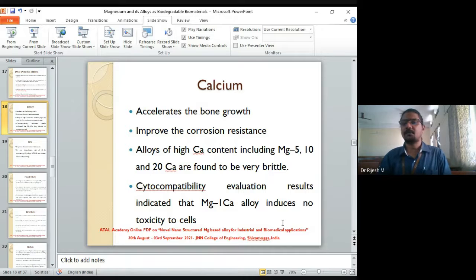Alloys of high calcium content, including magnesium with 5, 10, and 20 percent calcium, are found to be very brittle. Whenever you add calcium, corrosion resistance increases, but mechanical properties come down, is what we observe. Cytocompatibility evaluation results indicate that the magnesium 1 calcium alloy induces no toxicity to cells. So if you go for magnesium 1 calcium alloys, it is not as brittle as when you have 20.